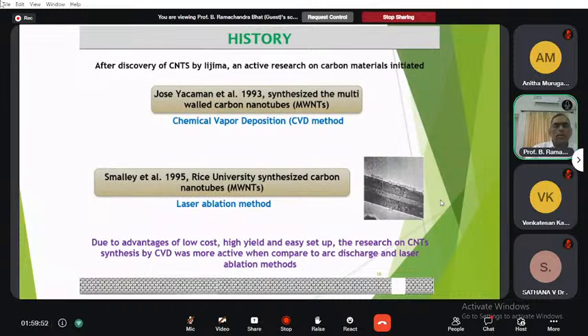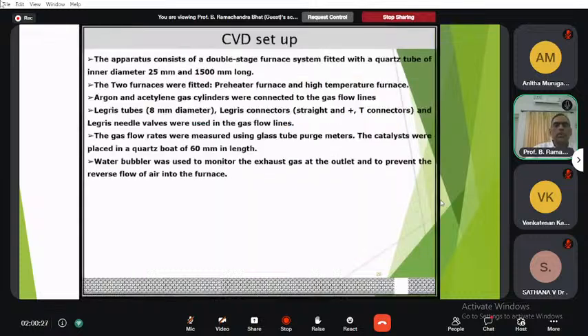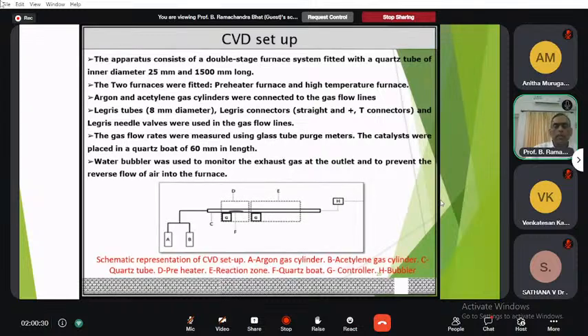And the chemical vapor deposition method was reported by Jose Yacaman and there are also laser ablation methods. So you can see this simple setup, the instrumental setup required for the synthesis of carbon nanotubes, where this is a two-furnace system. Sometimes one furnace is also used. There are two cylinders, one is the argon cylinder, another is the acetylene cylinder or the hydrocarbon cylinder to supply the precursor. And you have a quartz boat here, and it is kept in the quartz tube.